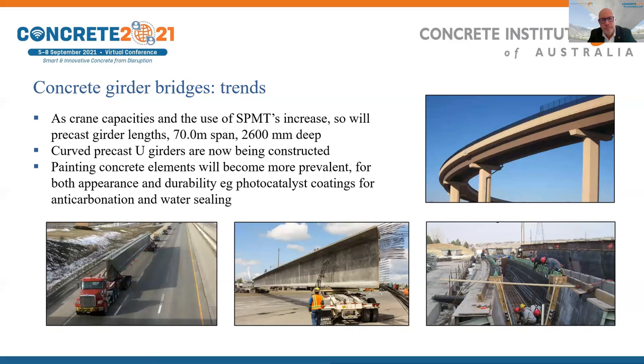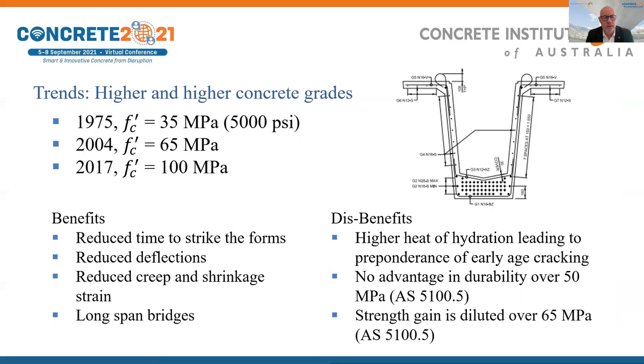Like to talk about higher concrete grades. When I had my first year out as a young bridge engineer many years ago in 1975, 5,000 PSI concrete was considered high strength. In bridges today, we'd use 40 or 50 MPa without even thinking about it as a status quo. In 2004, the Australian Bridge Standard provided provisions for 65 MPa, and in the latest revision of the standard, we've now allowed up to 100 MPa.